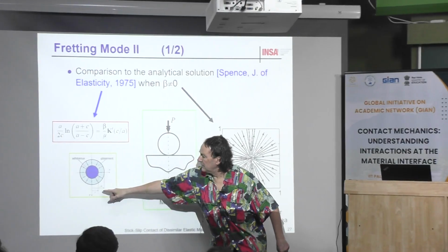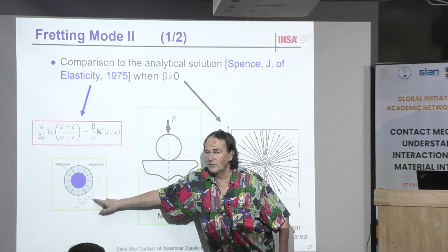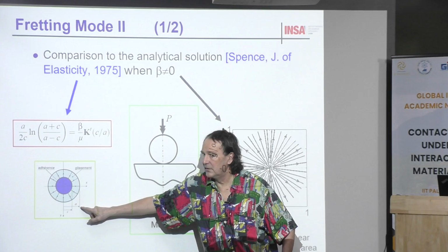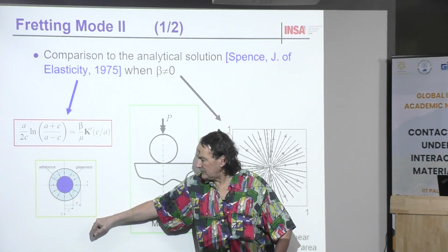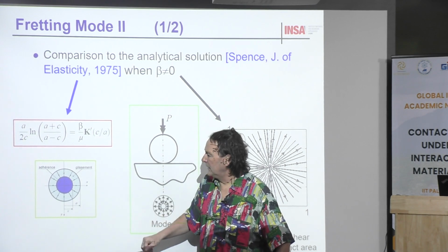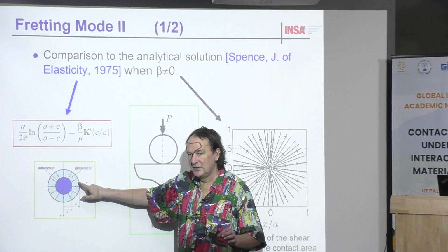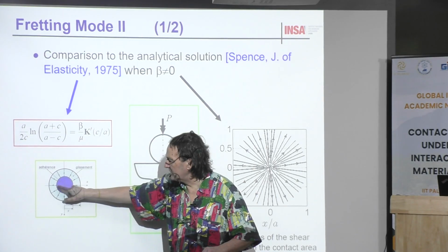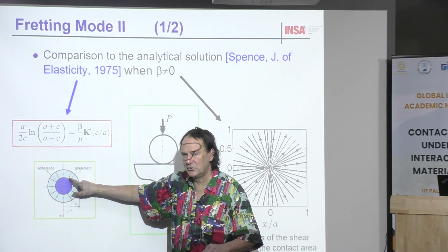Okay. C is this one, and A is this one. Okay. Stick here actually means not the shared region and unshared region you're telling me, because anyhow all are in stick only. In fact, in this domain, the shear stress equals the pressure times the coefficient of friction. And in this domain, the shear stress is lower than the pressure times the friction coefficient.